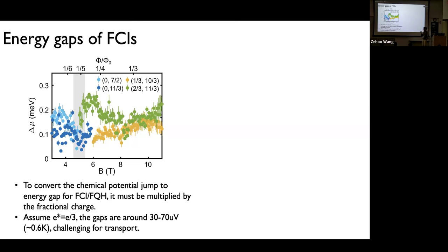The subtlety comes from when you want to estimate the energy gap for this kind of quasi-particle excitation, then you actually need to take into account the effective charge, the quasi-particle charge, which is in this case, if it's 1/3, the natural assumption is e over 3. And then you actually need to multiply that number. So the estimate that we got is 30 to 70 microvolts, around 0.6 Kelvin.